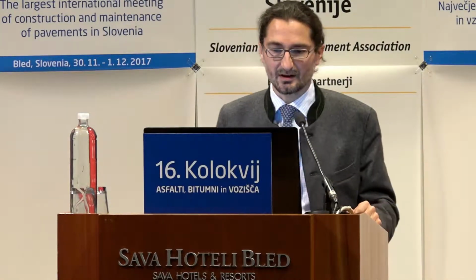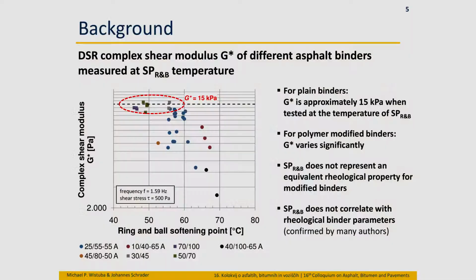And you see this dotted line in a range of 15 kilopascal, and all the plain binders are grouping around this line, which means that G star, the shear modulus, is approximately 15 kilopascal when testing plain binders at the temperature of the softening point. And for the other bitumen, the polymer modified bitumen, G star varies significantly. There is a wide scatter. And in the end, you can say the accuracy of the softening point for modified binders is 15 degrees Celsius, which is out of scope. So we cannot use this method.